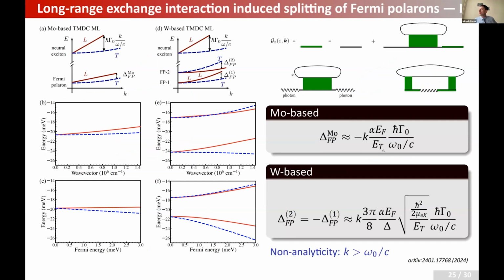I will show you just one formula. This is for molybdenum-based material. The splitting is proportional to the exciton splitting with a factor which is basically the Fermi energy divided by the trion binding energy. So you can say that the Fermi polaron inherits the splitting from the exciton, and that is why we have this small coefficient. The theory is valid for not too high Fermi energies, where the Fermi energy is much smaller than the trion binding energy. Otherwise, these trions and Fermi polarons become basically screened.